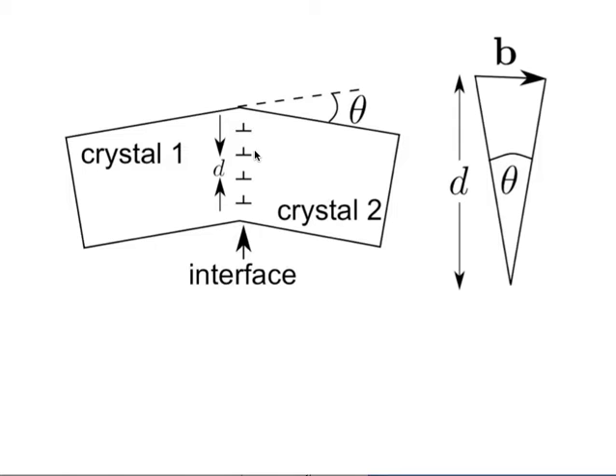You can see from the simple geometry here that if the dislocations have a Burgers vector b and their spacing is d, then we can relate that to the tilt angle theta by a straightforward equation: the tangent of theta upon 2 is equal to the Burgers vector divided by twice the spacing of that array. If theta is small, then 1 upon d will be proportional to theta. So these dislocations will get closer and closer together if the angle theta is large. They are inversely proportional.